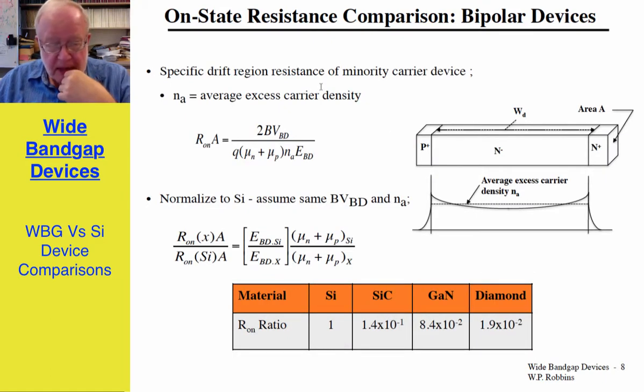switching losses, conduction losses. If you do a comparison for a bipolar device, one can show approximately that the ohms per square of the on-state resistance is given by the formula that I'm showing here: breakdown voltage divided by breakdown field strength, and 1 over the approximate excess carrier density. If we normalize to silicon and assume the same breakdown voltage and same excess carrier density, again I calculate the ratios, and again the wide bandgap materials show superior performance.